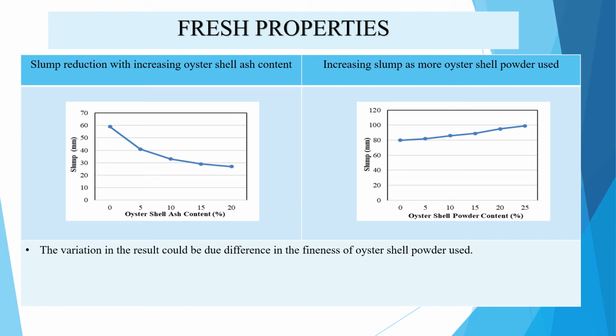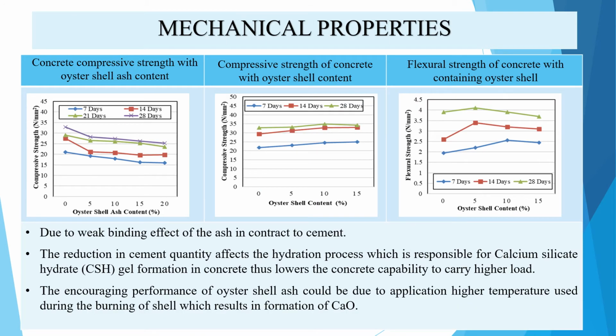Past researchers found different results for fresh properties as the fineness of the oyster shell powder used was also different. For instance, one researcher used powder passing a 75 micrometer sieve and found that slump reduced with increasing oyster shell ash content. Other researchers used oyster shell powder passing a 150 micrometer sieve and found that the slump kept increasing when the oyster powder was added. For mechanical properties, the strength decreases when an excessive percentage of oyster powder is added to concrete.